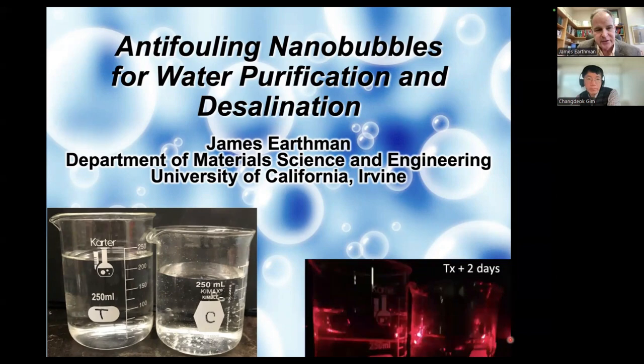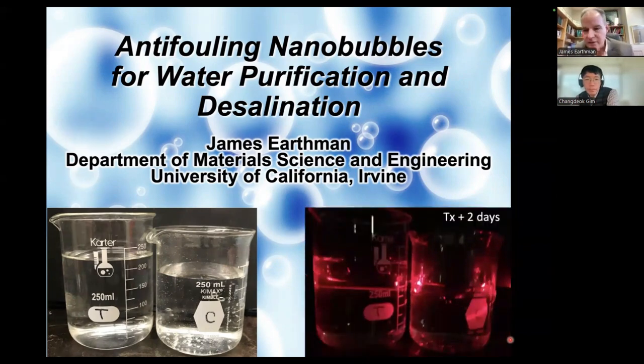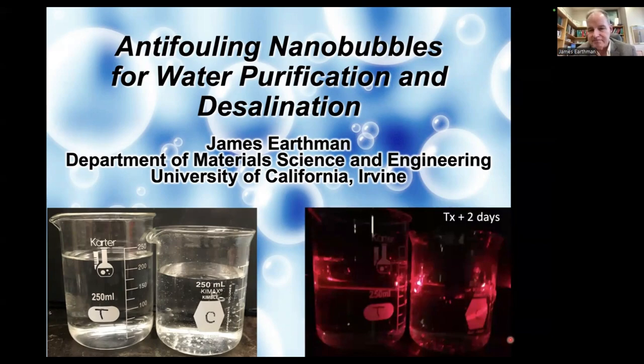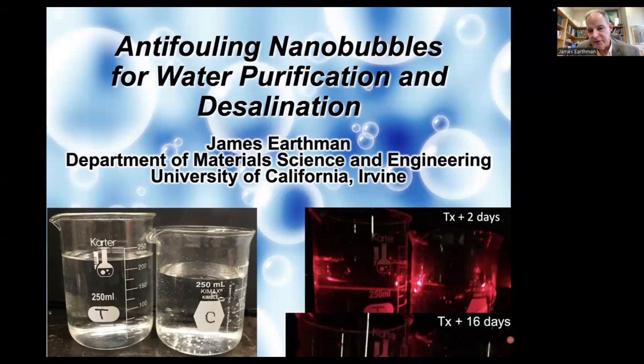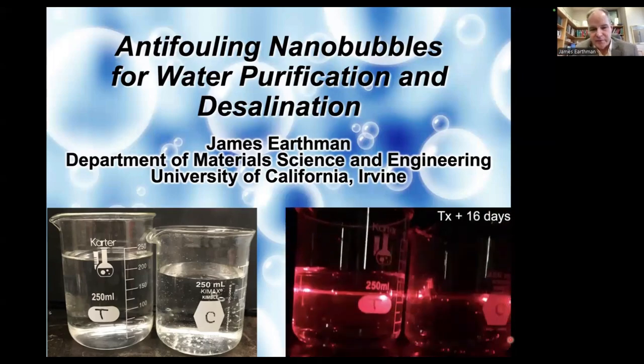T is for test. And if I shine a laser pointer through those two beakers at the same time, you'll see in the beaker with nanobubbles, and this is after 2 days of creating the nanobubbles, you can see a trace, a clearly defined trace through the beaker. It's actually on the other side of where the laser pointer is. I'm shining it from your right side and through both beakers, and you can see the trace pretty clearly in the beaker labeled T and not so clearly with the other beakers. So you can see that the nanobubbles are scattering light if it's collimated and from a laser. But in diffuse light, very difficult to see them. You can't really see those bubbles that are so small.